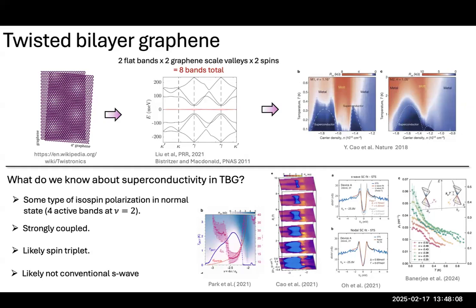And then maybe more compellingly, at lower temperatures now, the stiffness has been measured, and they find linear dependence with temperature. So this is also evidence that you have some type of nodes in your superconducting state and that you can't have this conventional S-wave superconductor.